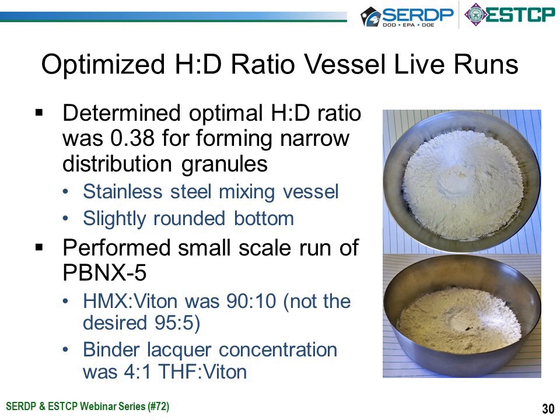We performed a small-scale run of the PBNX-5. Unfortunately, due to a slight miscalculation of the lacquer concentration, this run was done at a 90-10 instead of the 95-5 that we were originally shooting for. The binder-to-lacquer concentration was 4:1 THF to Viton. Slide 31, please.